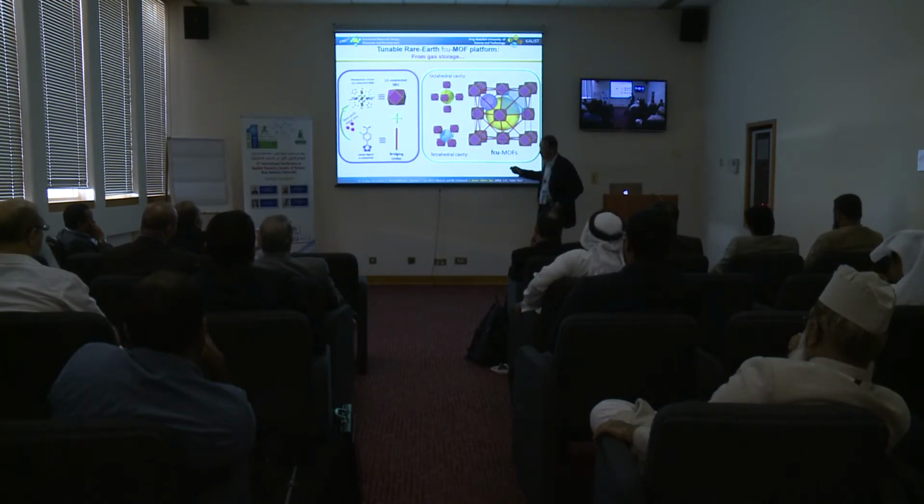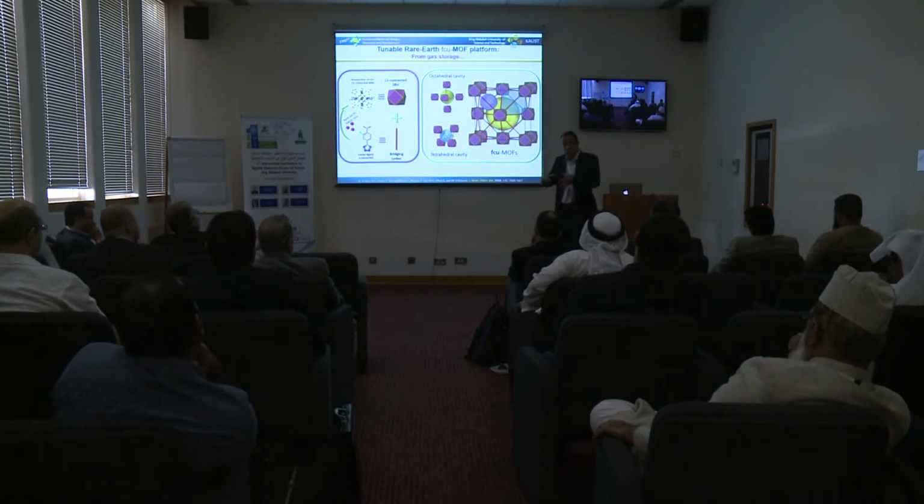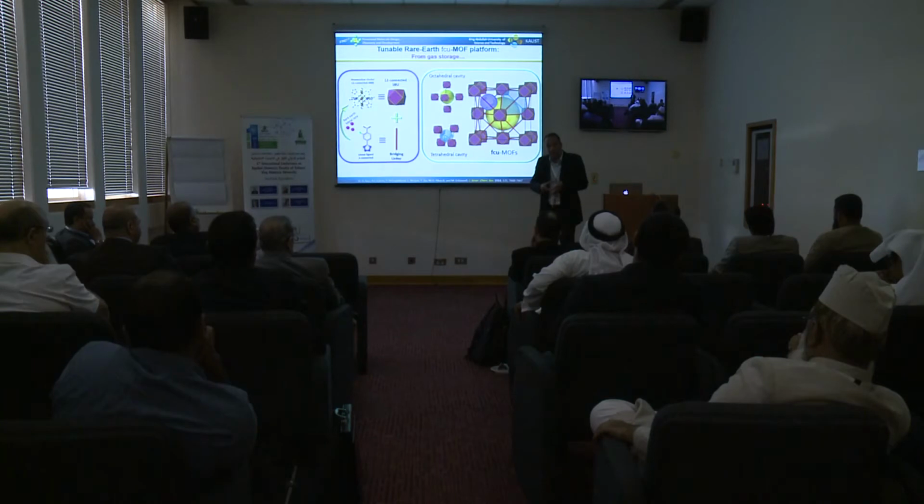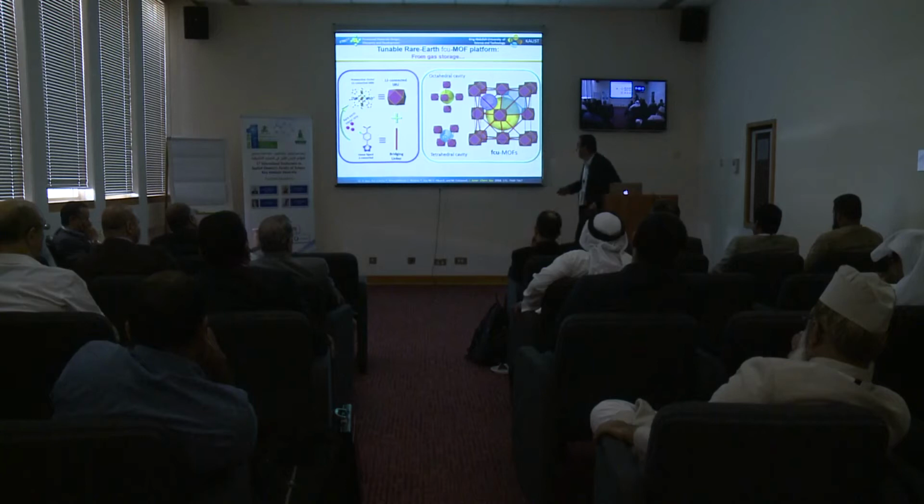And this link here, you have a triangle like this, and you can sense that this triangle has a large pore behind. If I reduce the linker, means I can still reduce my pore as much as I want. If you have normally a cube or a hexagon, you cannot do that. So by reducing this, means they can discriminate between my molecules. So the idea is to reduce even further to separate molecules that are of importance.